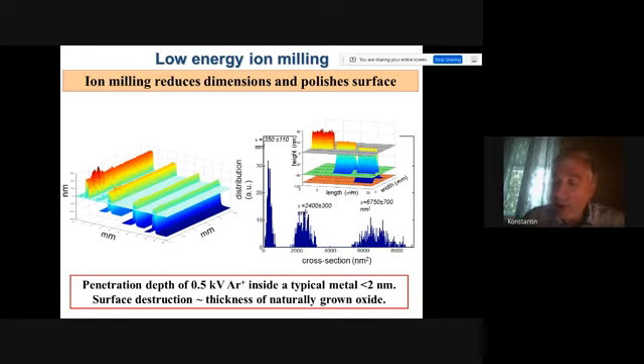A very typical question when I present this method is whether it is invasive or not. Everything depends on the kinetic energy of bombarding ions. If the energy is rather small, let's say half a kilo-electron volt, then the penetration depth of argon ions inside a typical metal is smaller than 2 nanometers. And 2 nanometers for metals, we are speaking about aluminum, titanium, or niobium, is just the thickness of a few interatomic distances which is chemically destroyed. Meaning that our method is basically non-destructive. It cleans the very few atomic layers at the surface.